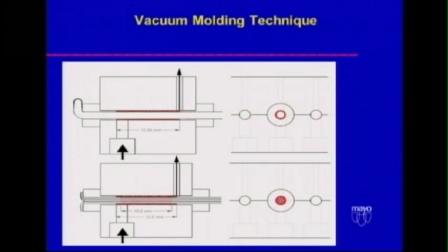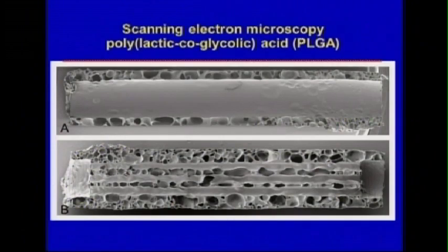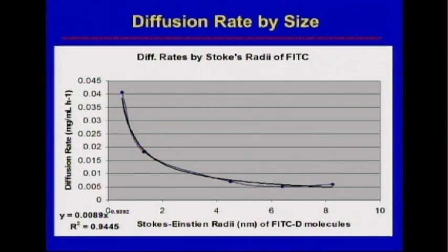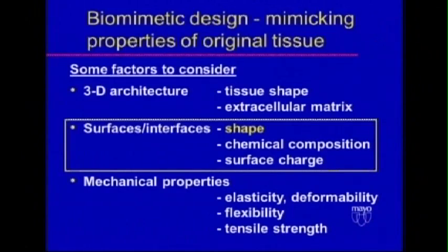This is another processing technique. Vacuum molding is how we make the nerve tubes, either single channel on the top or multi-channel on the bottom, with a porosity, as you see in the walls outside the channels, through which we can deliver things. Their diffusion rate changes by the radius, makes sense, and we can control that change via the composition and molecular weight of the polymers.